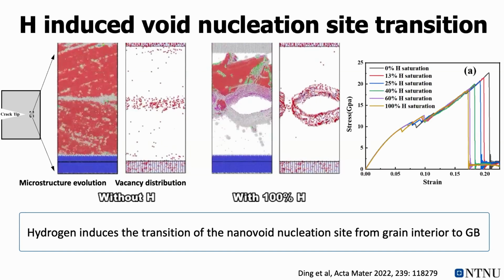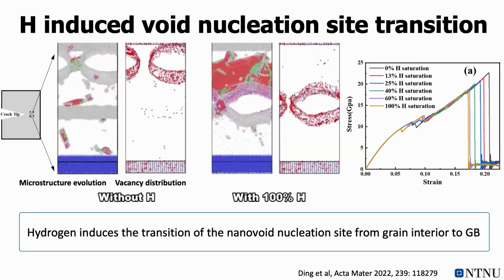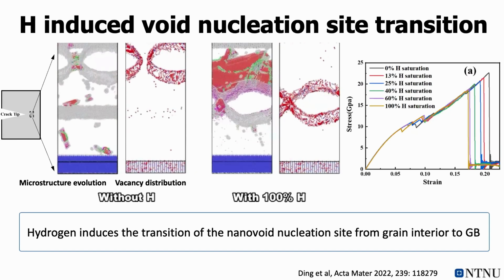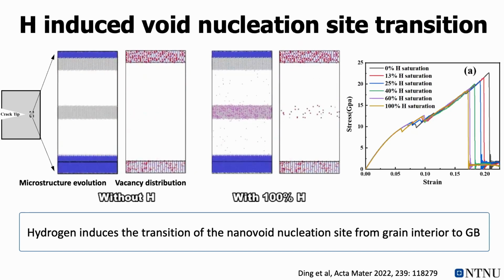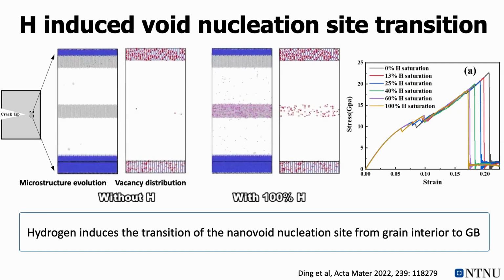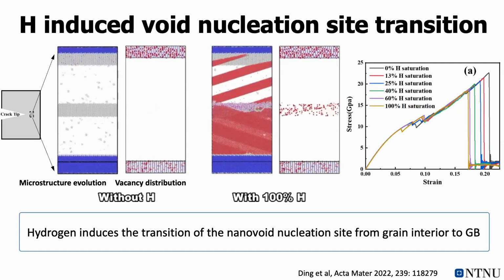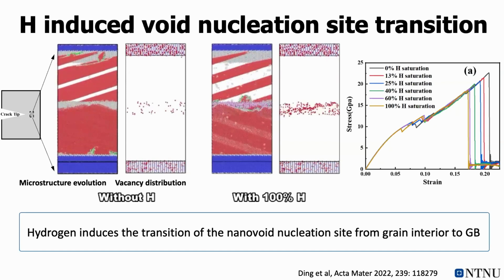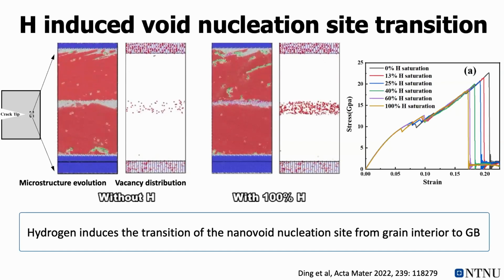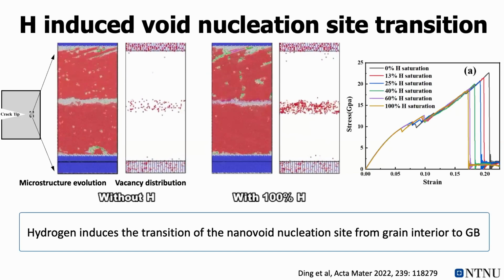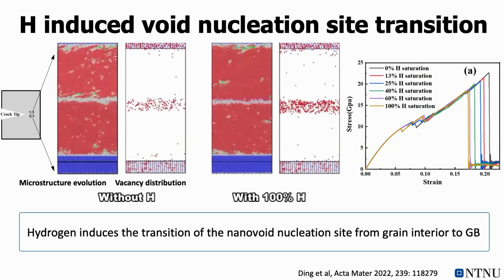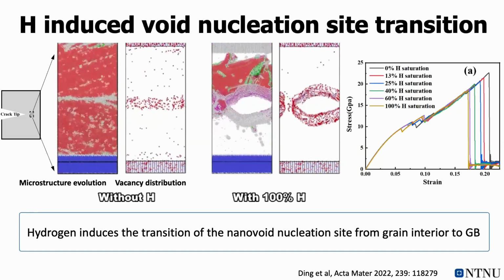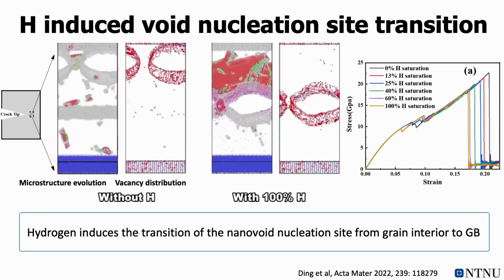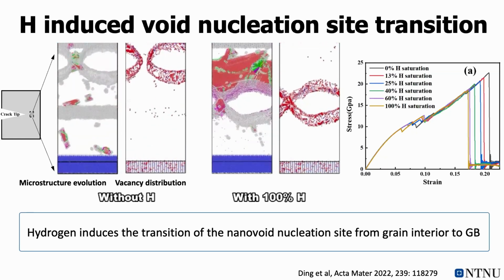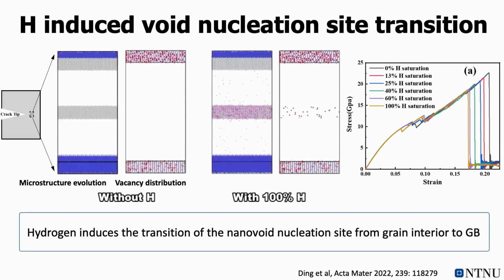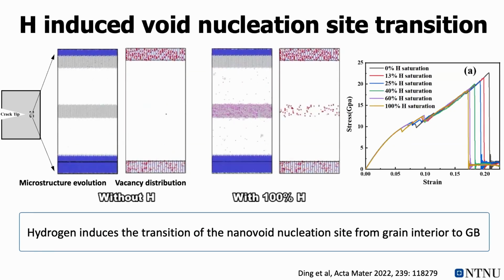And also, importantly, we see a difference in void nucleation and growth. Without hydrogen, it happens inside of the grain, while with hydrogen, it happens exactly at the grain boundary. We have demonstrated that when hydrogen enters the grain boundary, it stays inside the grain boundary. That's why those voids form and grow there. This is an indication that when hydrogen enters the material, we have a transgranular to intergranular fracture transition.